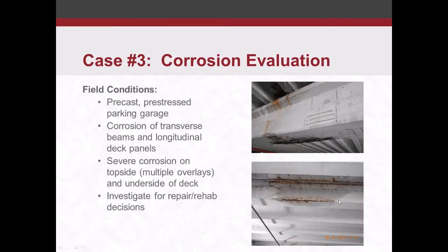This is one of the deck panels. It's got a spall right here on the underside. You can see the pre-stressed tendon exposed there. So some severe corrosion on the top side and on the underside. The top side had multiple overlays. Some of the overlays were asphalt, some of them were patches. So we really couldn't do our half cell testing, which is what we did on this particular project. We couldn't do it on the surface because of those overlays.